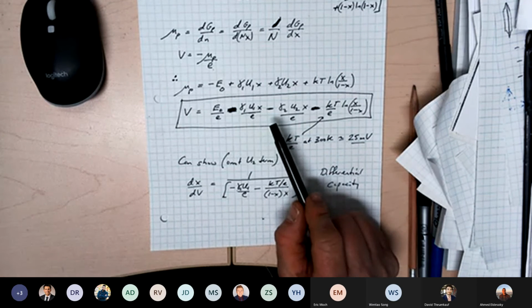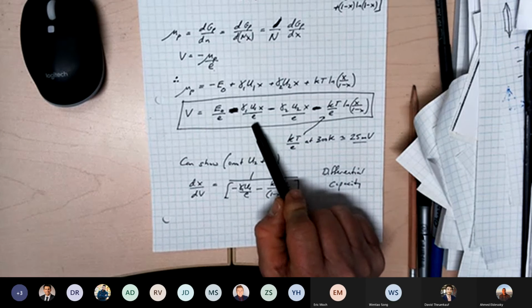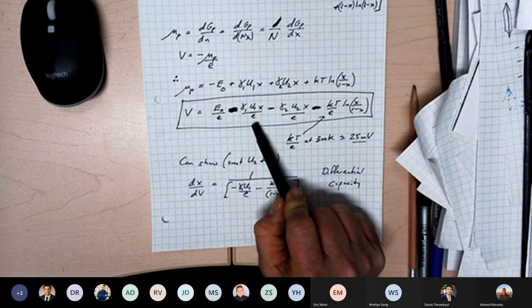Thanks. Okay, so now let's talk about interaction energies. Let's talk about Mo6Se8, where the lithium atoms are spaced by 8 angstroms, and it's a metal. And now let's talk about titanium sulfide, where the lithium atoms are spaced by 3 angstroms, and it's a semi-metal. Which do you think has the greater interaction energy, titanium sulfide or Mo6Se8?